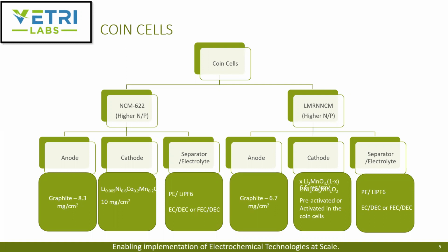On the anode, they choose graphite at 8.3 milligrams per centimeter squared loading. On the cathode for NCM, it's 10 milligrams per centimeter squared. The separator electrolyte is poly PE with LiPF6, and they use two different electrolyte systems: EC with DEC, and FEC with DEC. For the lithium manganese rich materials, the anode loading is 6.7.